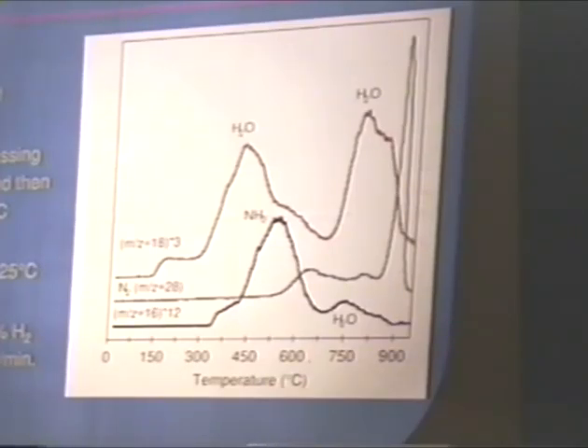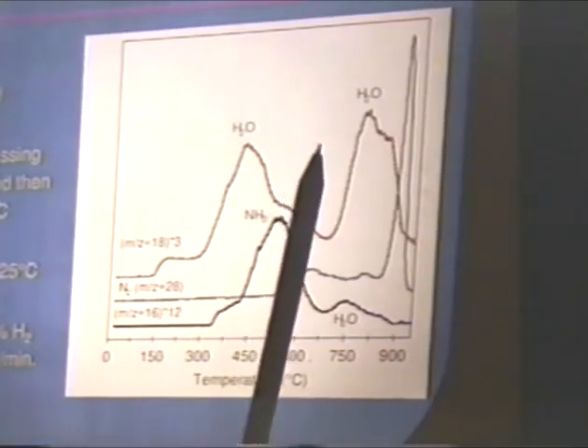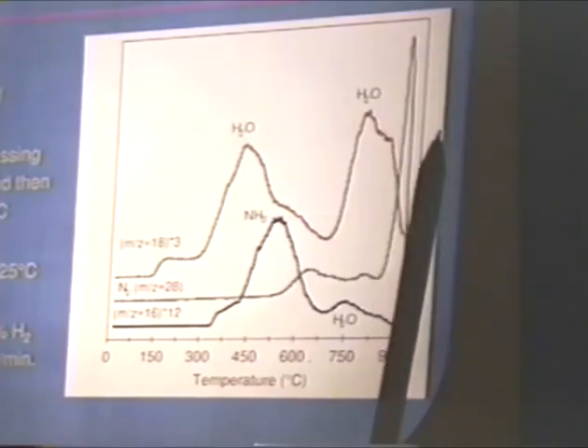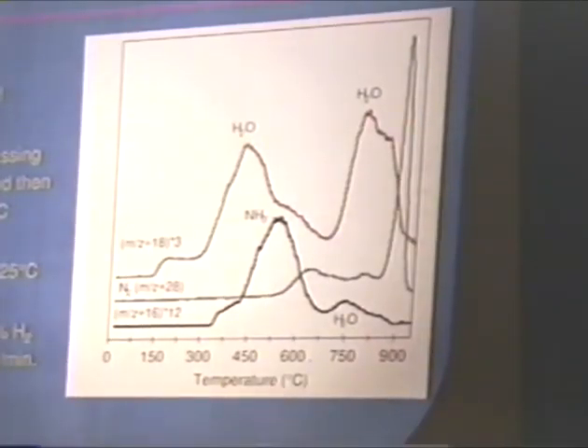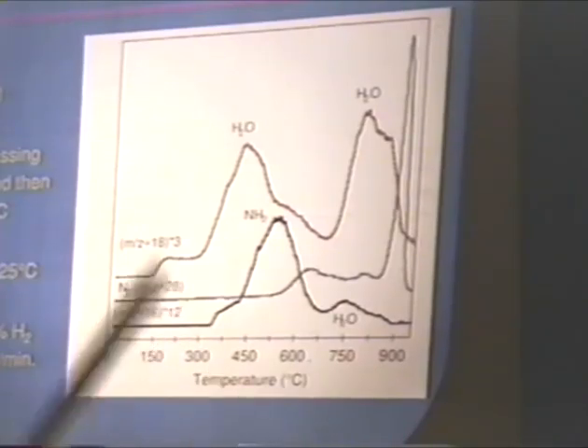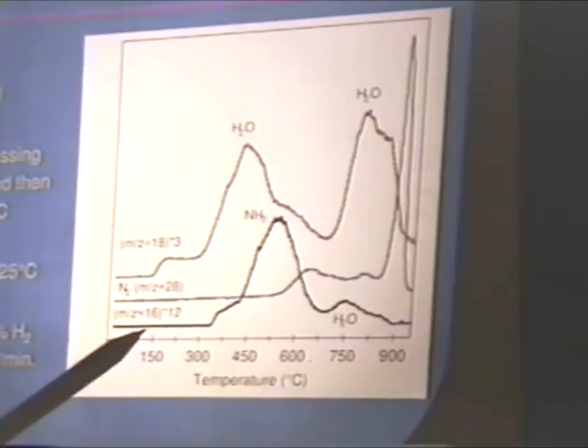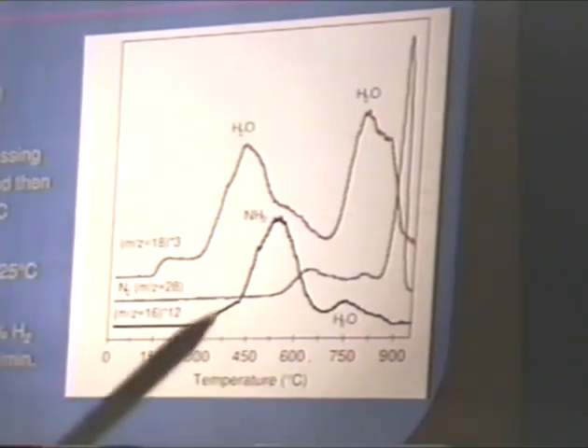Now, I will go back and compare some of these results with the X-ray diffraction characterization that we have done. What we have done in the X-ray diffraction was abort the TPR experiment at this point, and then abort it again at this point, and without exposing the samples to air, do an X-ray diffraction experiment on them. Now, before I go into that, let me also mention the nitrogen and ammonia signals.